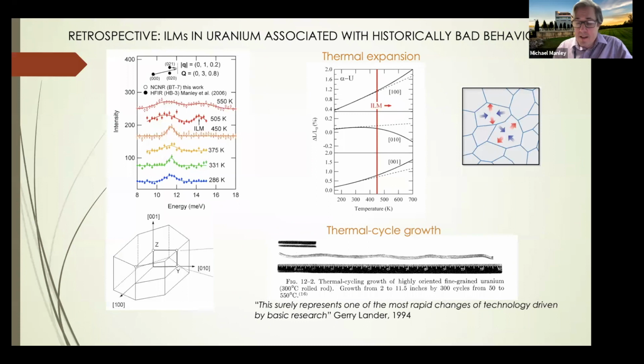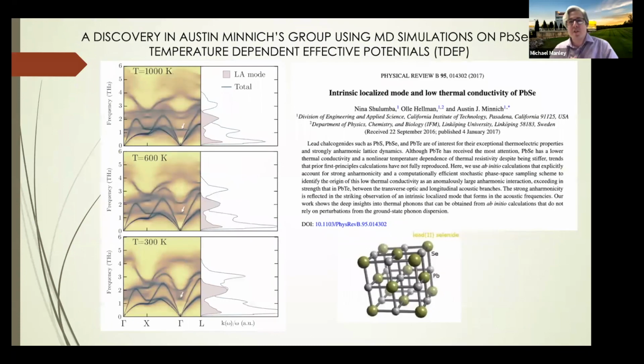So I needed advances. Something happened a few years ago at Caltech. There was Austin Minnich's group in the mechanical engineering department there. They were improving their simulations of phonons, and a lot of this has to do with Olle Hellman, who developed this technique called temperature-dependent effective potentials. Essentially, the ideal thing you want to do with a first principles calculation when it comes to phonons is what they call ab initio. You want to basically recalculate the electronic structure at every instant in a molecular dynamics simulation. That's the way to be exact, right?